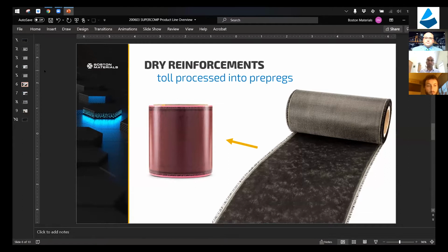We use a water-based slurry coating process to align the fibers on various substrates and films. Here I'm showing on the right-hand side a 3K carbon fiber fabric that has the Z-axis milled carbon fiber. And we stabilize this as a dry reinforcement. So it has a very trace thermoplastic binder, so you can handle it just like a dry fabric. And then we prepreg that with a thermoset epoxy, like a hot melt epoxy.